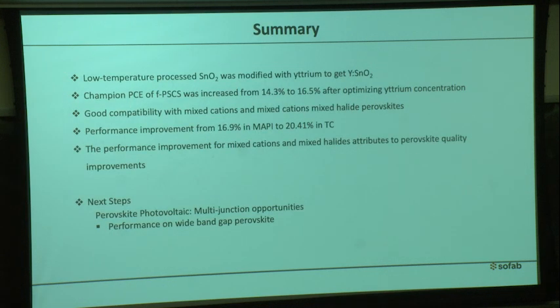That's why in this section, by elemental doping on the tin oxide, we were able to increase the power conversion efficiency from 14% to 16%. After that, in the second step, we changed the perovskite composition. By changing the perovskite composition, we were able to get power conversion efficiency up to 20%, which is incredible for the flexible perovskite solar cell.